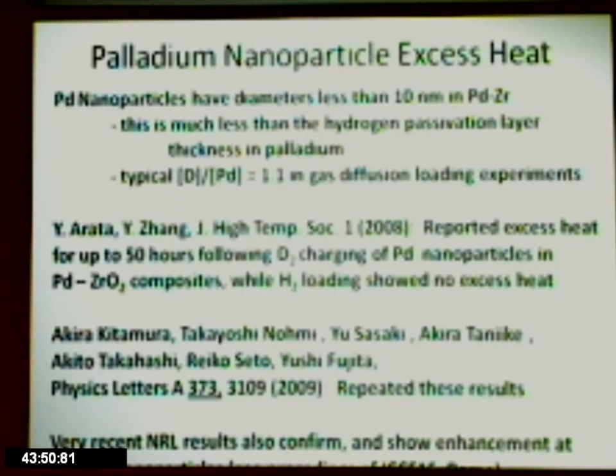So just by gas diffusion at ambient pressures, you can get a loading of like 1.1, and 0.88 seems to be necessary for any excess power observation. So this is the easy way to do it.